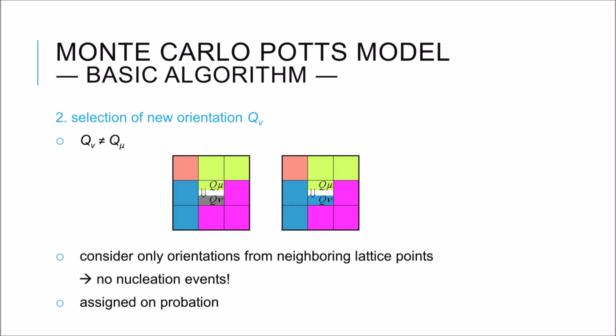You could choose any orientation. Then you are going to reject much more, and hence your simulation temperature will be different. Or if you select not from all neighboring lattice points, but just from the neighboring grains, the orientations, it's also always slightly different. But the basic way of how to do it is the same. Take a circular grain, put it into a larger matrix grain, do the simulation for different simulation temperatures, and you'll see at some point your area change rate should be minus 2 pi.